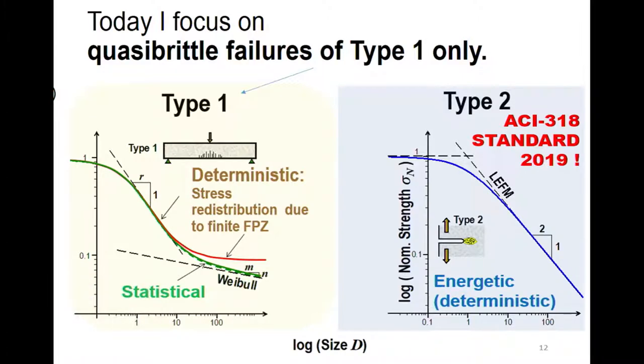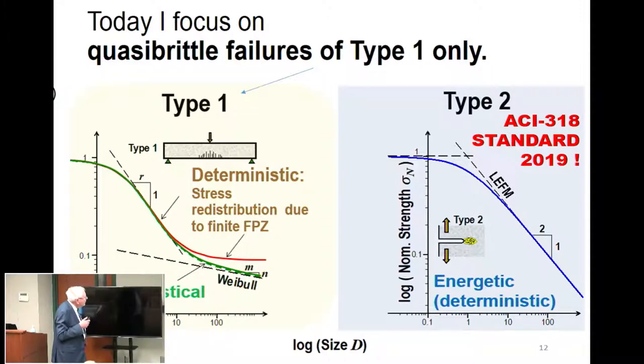I will discuss this for one type of size effect. There are actually two types of size effect in quasi-brittle structures. Type 2 is essentially deterministic. It occurs when a stable crack can grow large before the maximum load. So in concrete structures, if you load a concrete beam and grow a crack, 80% of the crack growth is still stable. Most reinforced structures are like this, and you get this kind of distribution, which, by the way, 35 years later is coming into the ACI code. I will not talk about this. I will focus on type 1.